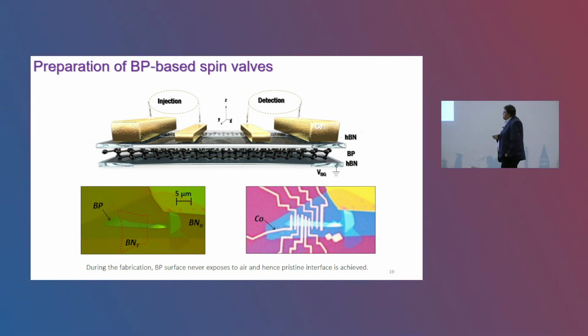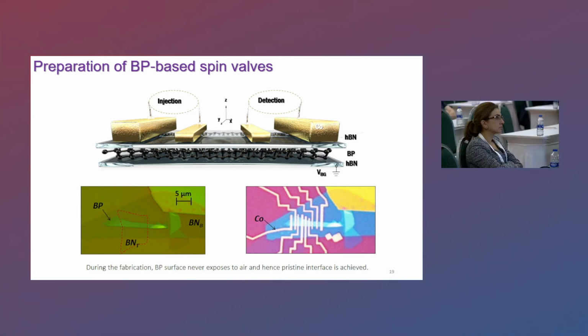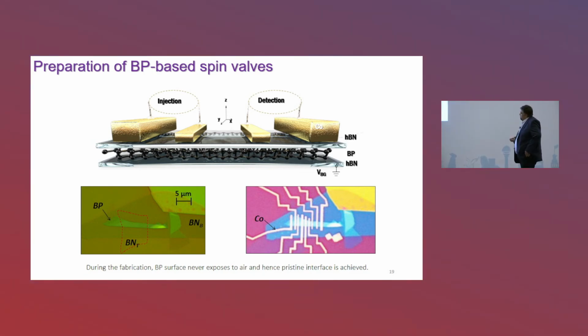So for that, what you do is introduce a tunnel barrier. Therefore, we are using these 3 layers of hBN, which is optimized to be the best in our case, as a tunnel barrier. And the boron nitride that you see underneath is again sandwiching it so that it's completely air stable. After you make the device, you can just take it out and complete the electrode preparation. These are the optical pictures before and after the metallization process.